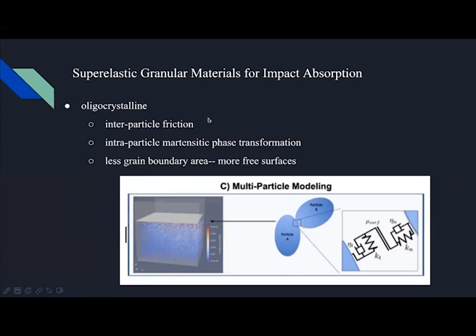Oligocrystalline is one of these materials, and it's a new class of shape memory materials which can dissipate mechanical energy through interparticle friction and intraparticle martensitic phase transformation. A unique feature of the oligocrystalline is that its total surface area is greater than the total grain boundary areas. As you can see from the graph, the contact area of these two particles is far less than the surface area, which gives them more free and confined surfaces rather than rigid boundary areas.